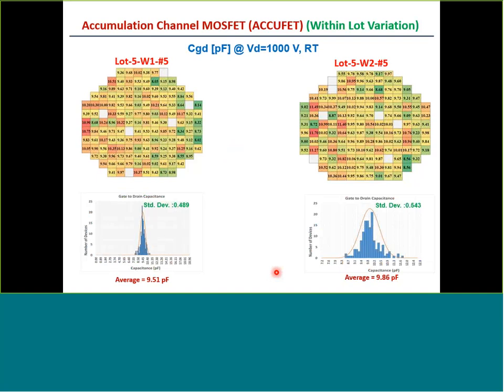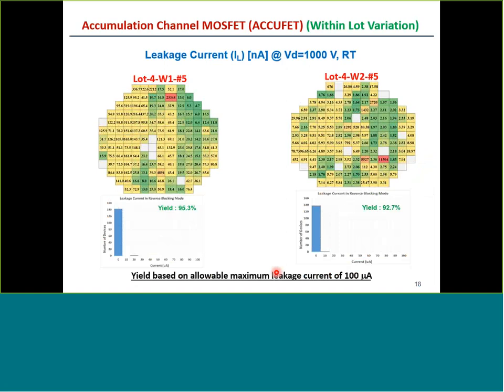In terms of the capacitance, we have monitored all the different types of capacitances, but I want to stress CGD because it's a measure of the switching speed and losses. So the CGD is usually quantified at VD of 1,000 volts in data sheets, so that's what we have given here. And you can see again the distribution is very uniform and has a very small standard deviation. In terms of leakage current, these devices have the leakage currents in the nanoamp range, and if you look at the distributions, the values all fall well below 100 microamps.